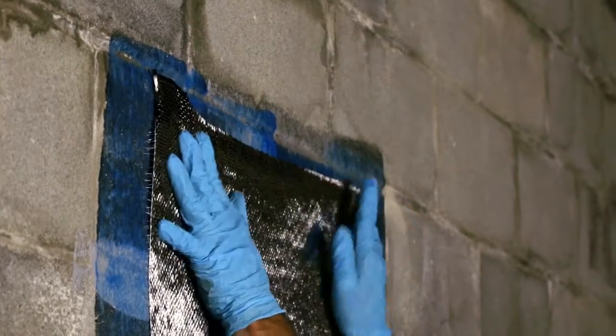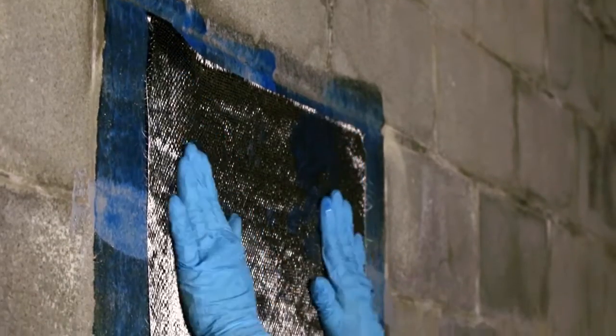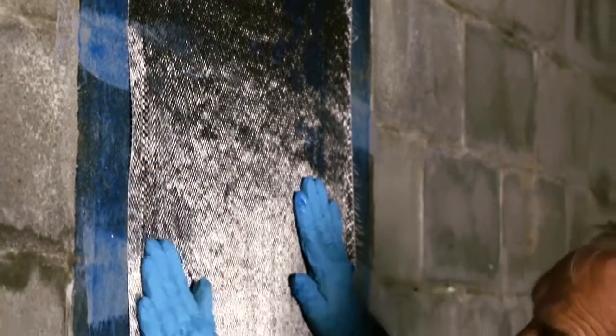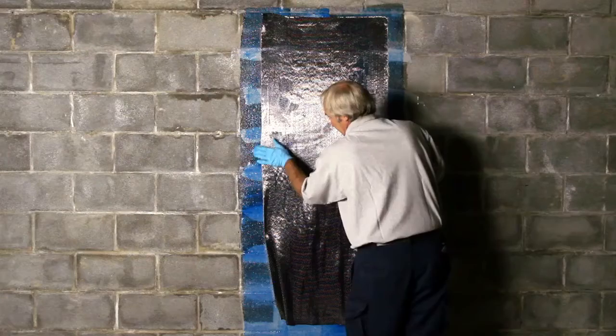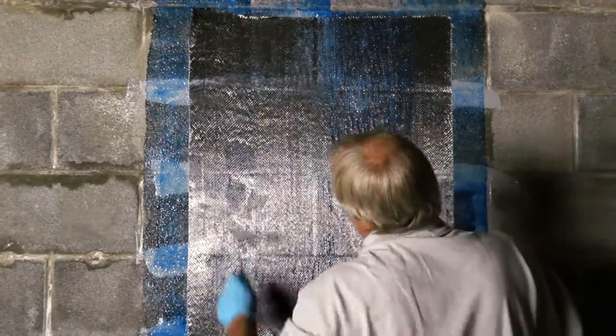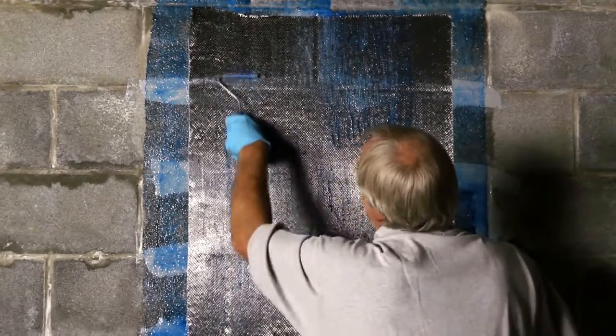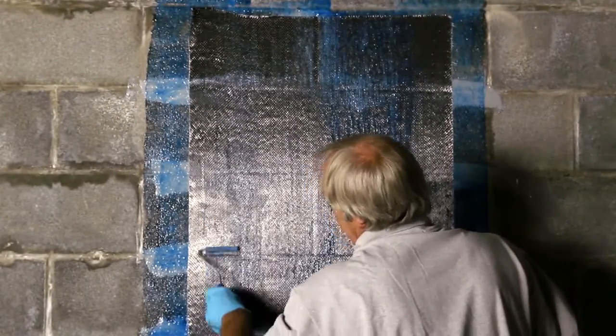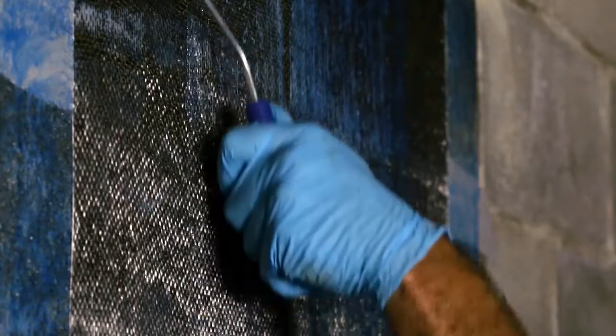Once it's applied, place the reinforcement fiber into the first coat. It goes up like wallpaper. Once the material is tacked in place by hand, use the ribbed roller to push the adhesive between the fibers and press out any pockets of air from underneath it. Roll the ribbed roller in the same direction as the fiber. It works best when you roll up from the center to the top and down from the center to the bottom.